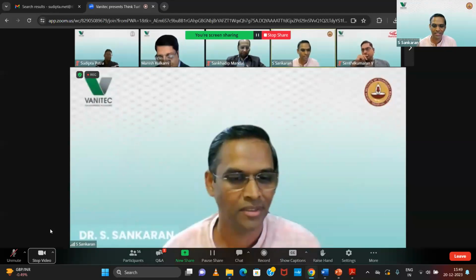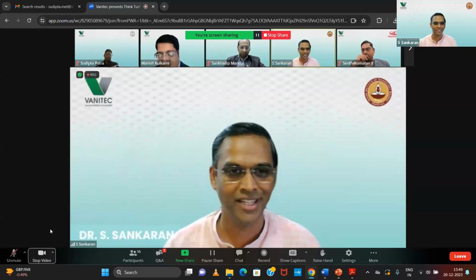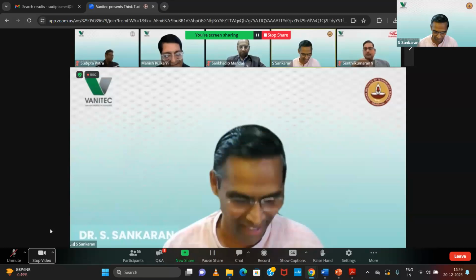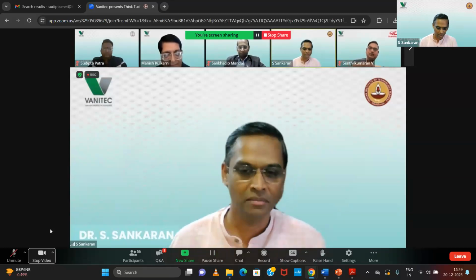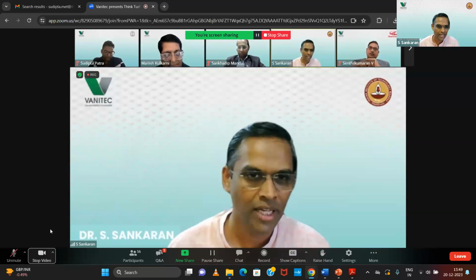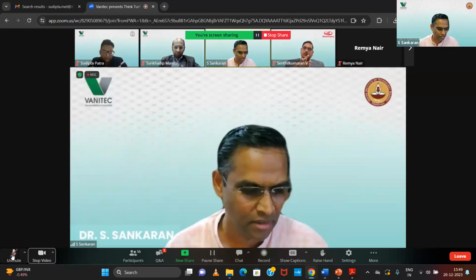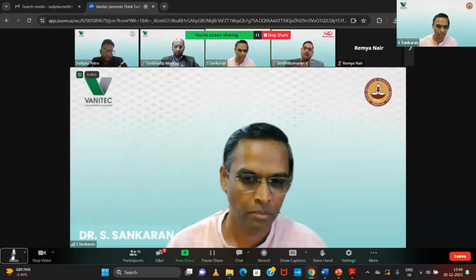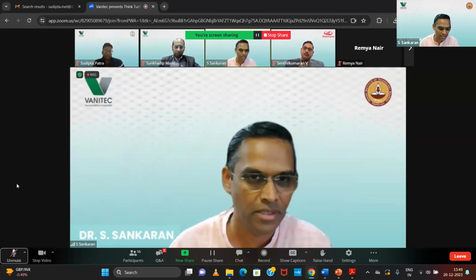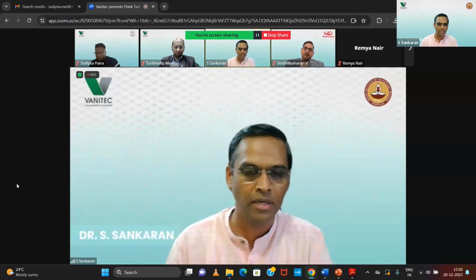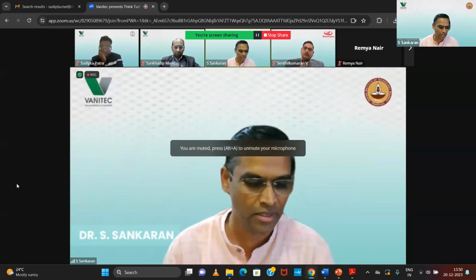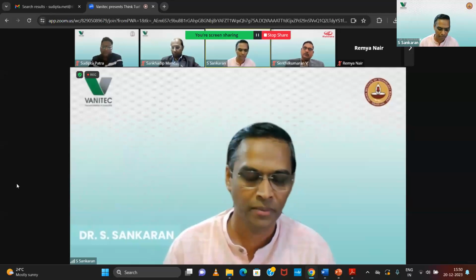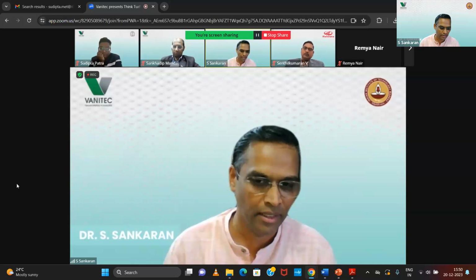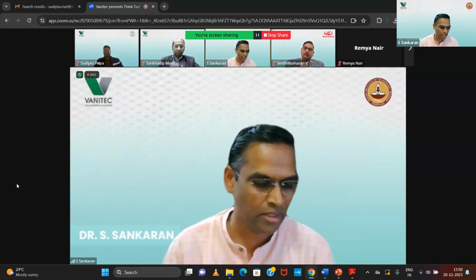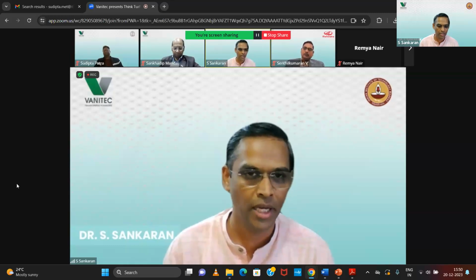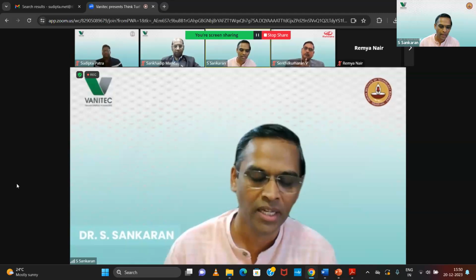Yeah, thank you, Dr. Manish. I have not prepared any slides, but I was told that it's a panel discussion. So, working with vanadium microalloy steel, for me, it is more than 20 years now. I started working with vanadium microalloy steel for producing multi-phase microstructures during my PhD days. That is 38MnSiVS5, that grade, which these days Kalyani Group is producing. And there the challenge was, since the microstructure is multi-phase, characterizing these precipitates in each individual phase is a huge challenge.